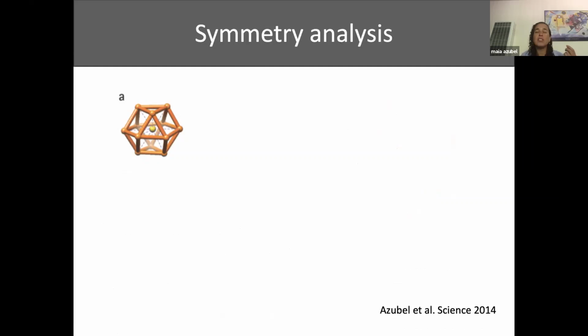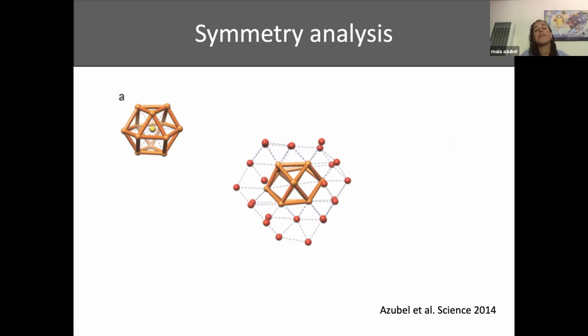About the symmetry, it's not completely true that the cluster has no symmetry at all. The center of the cluster is a cuboctahedron with an atom in the middle. About half of the atoms extend into what is an FCC-like symmetry, and then the most exposed gold atoms are quite deformed. And again, that has to do with the fact, and I will say it briefly because I think that it's fascinating, that with the 3 MBA instead of the 4 MBA, you have the carboxylic group in a meta position, and that carboxylic group can interact with the core. That is part of the suggestion that Mika and Hannu are making for why these 3 MBA deform the very symmetrical clusters that you can see in other cases.